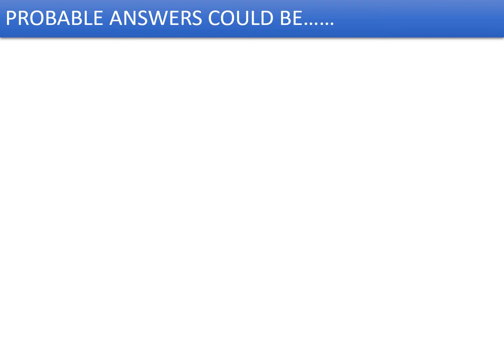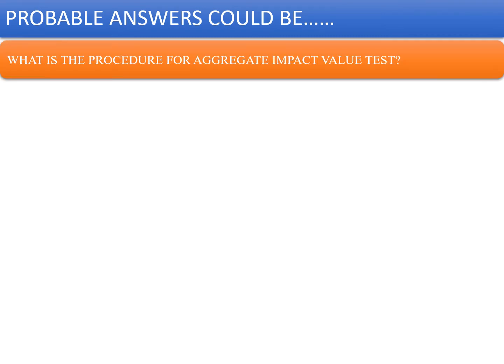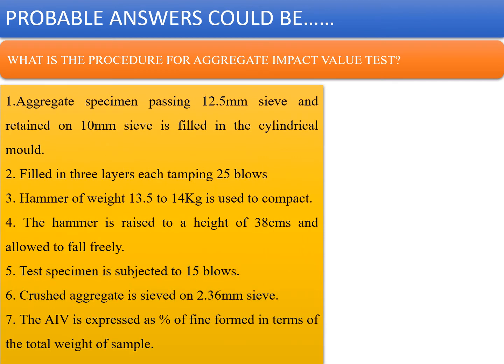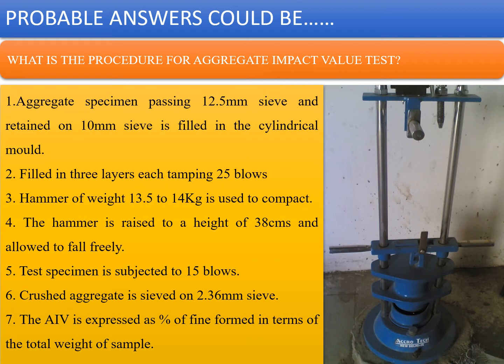Next question is, what is the procedure of the aggregate impact test? If you see the procedure, you have to first make the sample with 12.5 mm passing and 10 mm retained aggregates in a cylindrical mold. Then you have to fill the mold in 3 layers, each tamped with 25 blows. A hammer of weight 13.5 to 14 kgs is used to compact the material in the cylindrical mold. The hammer is raised to a height of 38 centimeters and allowed to fall freely. The test specimen is subjected to 15 blows. The crushed aggregate so obtained is sieved through the 2.36 millimeter IS sieve, and then the aggregate impact value or AIV is calculated and expressed as percentage of fines formed in terms of the total weight of the sample.